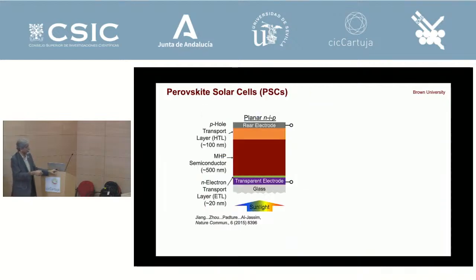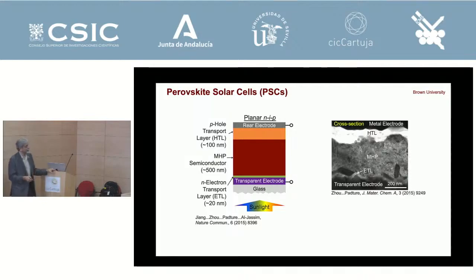For example, this is a NIP structure. This is basically five layers. You have the transparent conducting electrode, light comes in this way, then you have an N-type layer, the absorber, a P-type layer, and then an electrode. And this is a structure, the TEM pictures from my group, early pictures that show the cross-sectional structure.